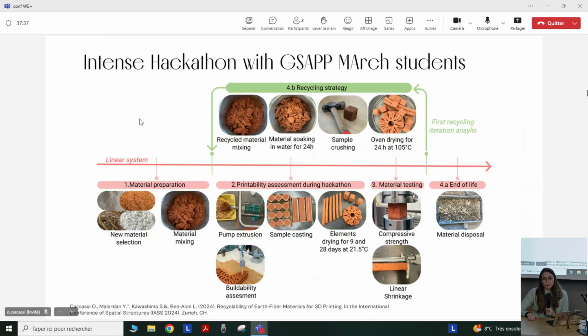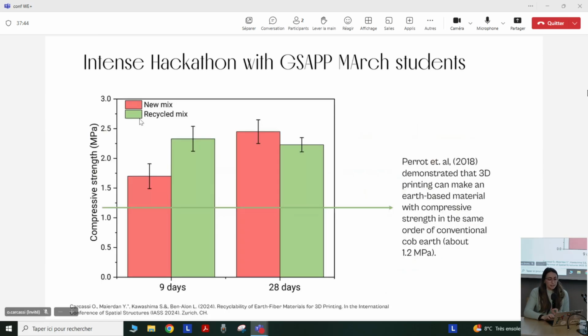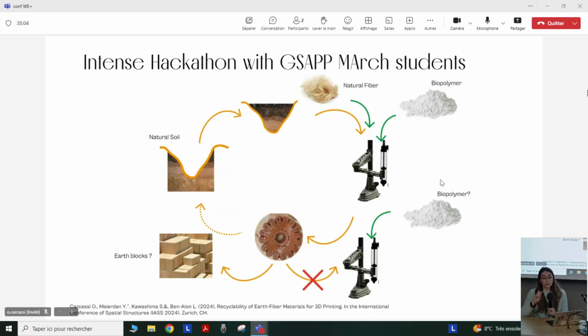After we completed the material, we soaked it again, and then we tried to print it again and create this circle. First, we tested the compressive strength of both the new and the recycled mix after 9 days and 28 days. And what was very interesting for us to see is that the strength remains more or less the same. So this suggested that our materials can be reused, without losing any of the properties. But nonetheless, when we tried to print it again, we realized the materials had a lot of clumps inside. So in order to print it again, we need to add more biopolymers.